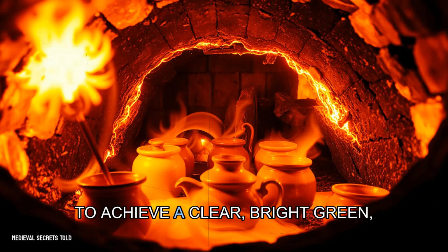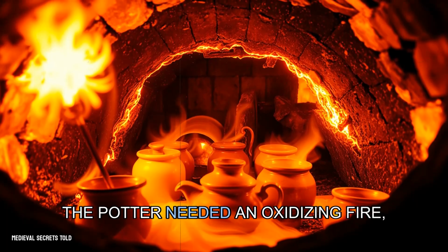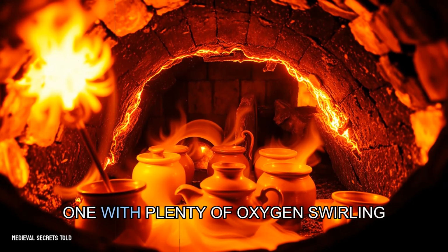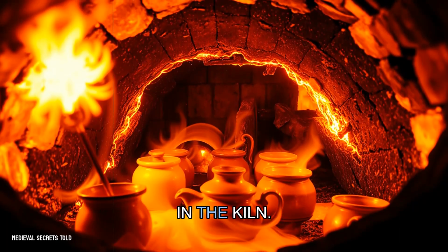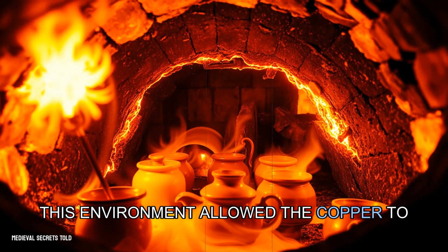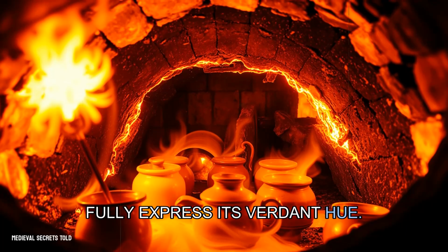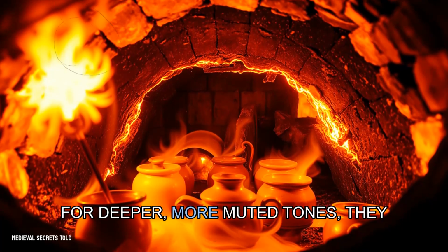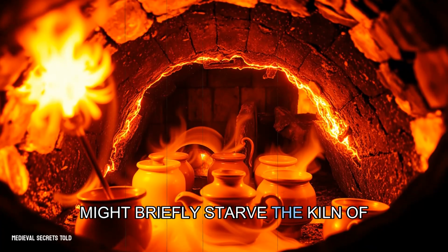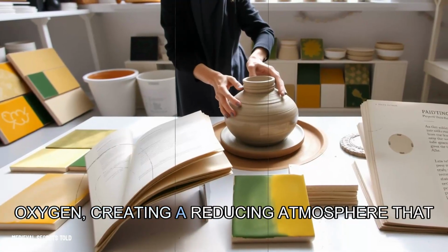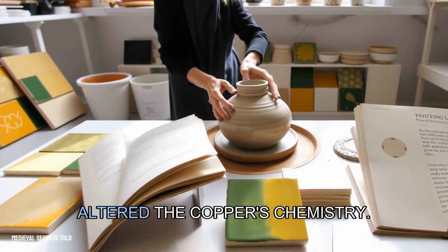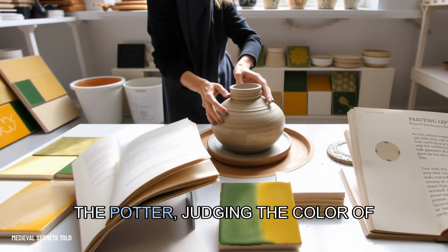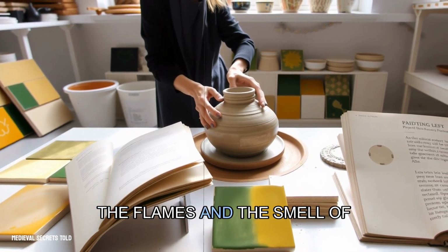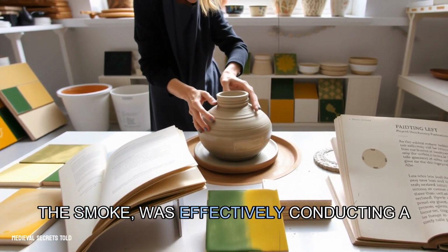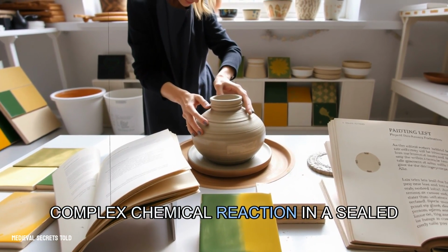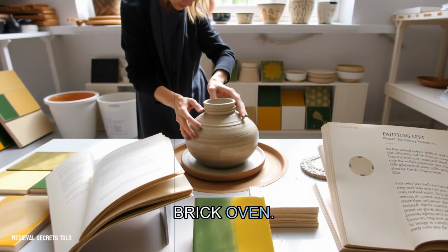To achieve a clear, bright green, the potter needed an oxidizing fire, one with plenty of oxygen swirling in the kiln. This environment allowed the copper to fully express its verdant hue. For deeper, more muted tones, they might briefly starve the kiln of oxygen, creating a reducing atmosphere that altered the copper's chemistry. The potter, judging the color of the flames and the smell of the smoke, was effectively conducting a complex chemical reaction in a sealed brick oven.